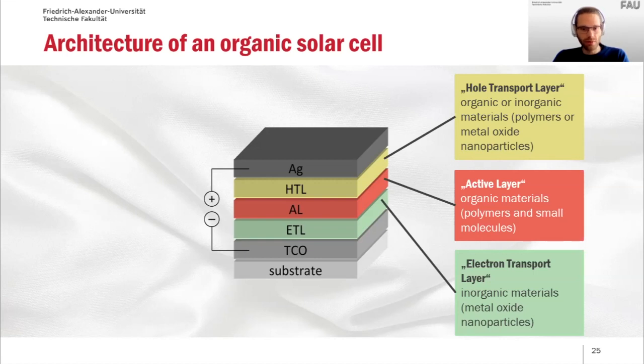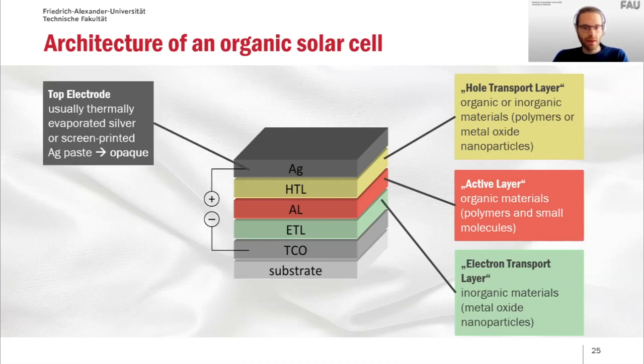And now, most importantly for this talk, are the electrodes. On the one hand, we have a top electrode, which is also called back electrode, because the light comes from the bottom through the substrate into the solar cell, and this electrode is on the back side, which is usually a thermally evaporated silver or a screen printed silver paste electrode. And the drawback is, of course, that those materials are opaque, so you can't look through the module.